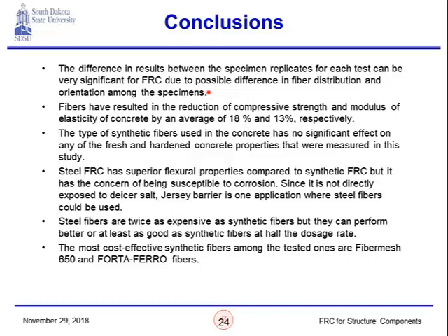which we believe is due to the fact that the distribution of fibers, and specifically the orientation of fibers, are very random. Once we mix and cast the concrete, we really have no control over the orientation of each of the fibers. So they are randomly oriented within the concrete. And this basically